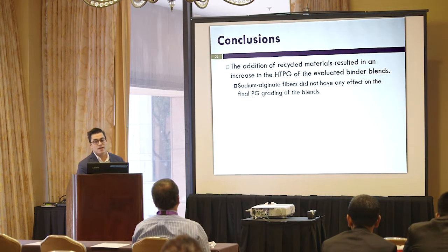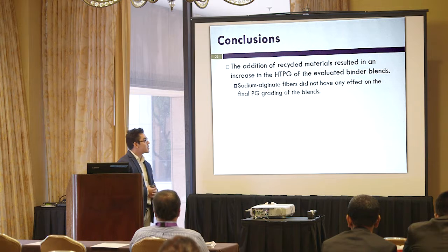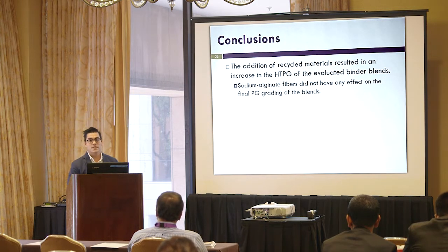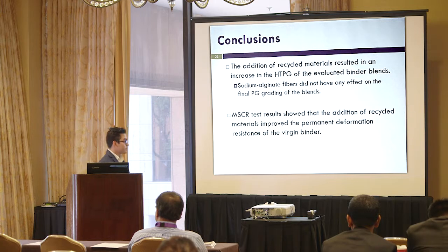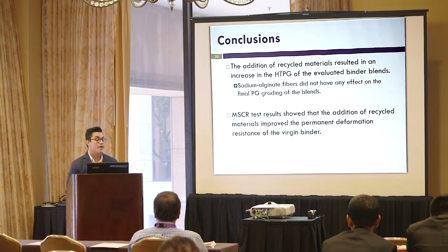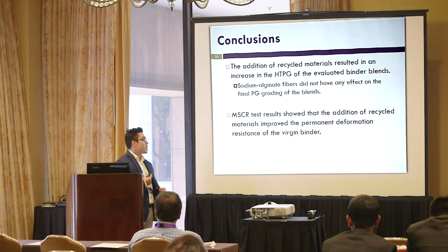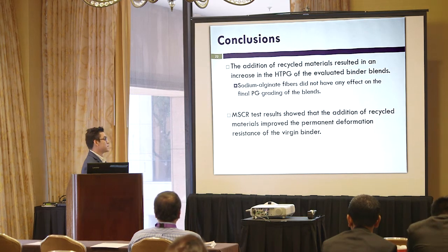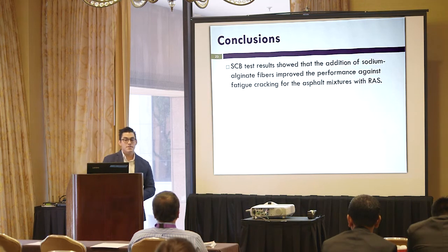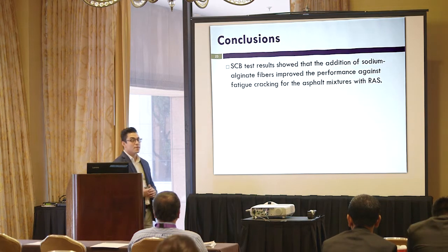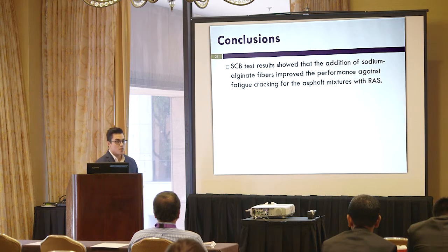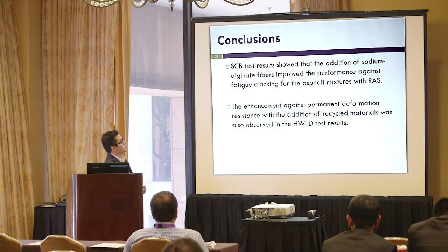adding a recycled material increased the high temperature performance grade of the binder blend, and that the sodium alginate fibers didn't have any effect on the PG grading. MSCR test results show an improvement in the permanent deformation performance when we are adding recycled materials and fibers. The SCB test results show that whenever we were adding sodium alginate fibers in the mixture containing 5% RAS, we recovered some fracture resistance performance that we lose by adding the RAS.